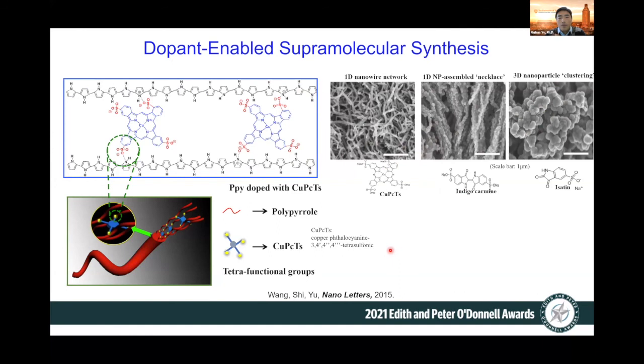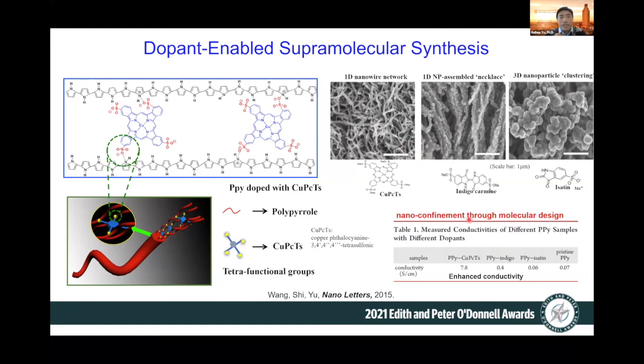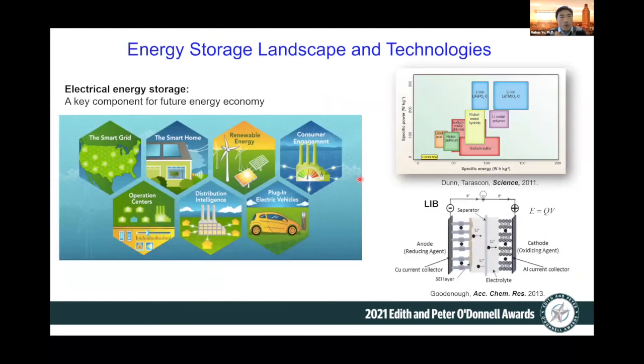And moreover, the nanostructure and the confinement effect due to this formation of fiber give very different physical properties. One example is electronic conductivity. If you use this CuPCTS, it can give about 8 Siemens per centimeter, so it's 800 Siemens per meter. And if you use isatin or pristine polypyrrole, they are 2 orders lower in terms of electronic conductivity. So let me show you how these synthetically tunable structures of the conducting polymer hydrogel can be used.